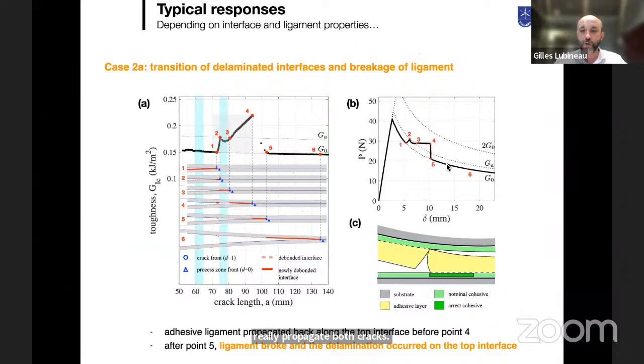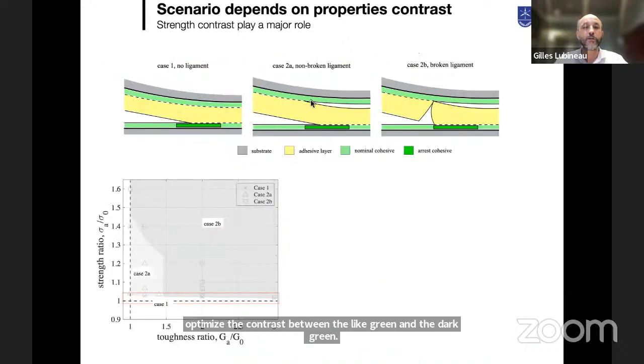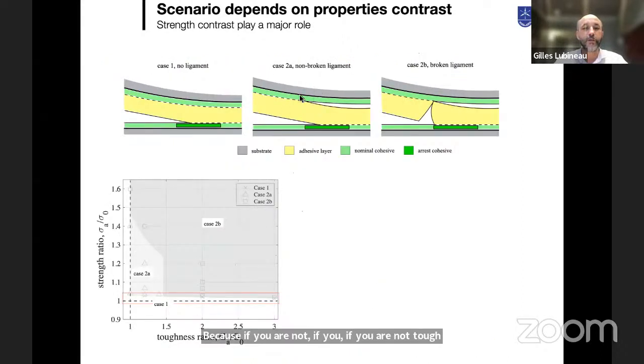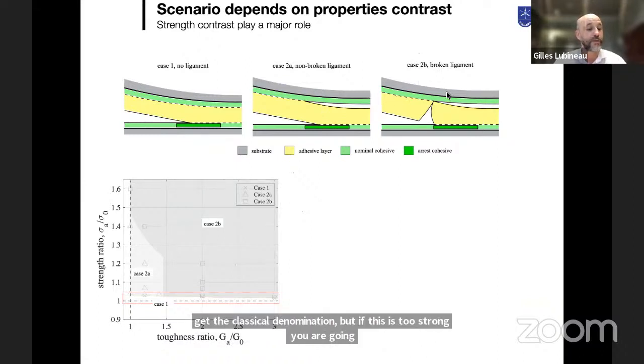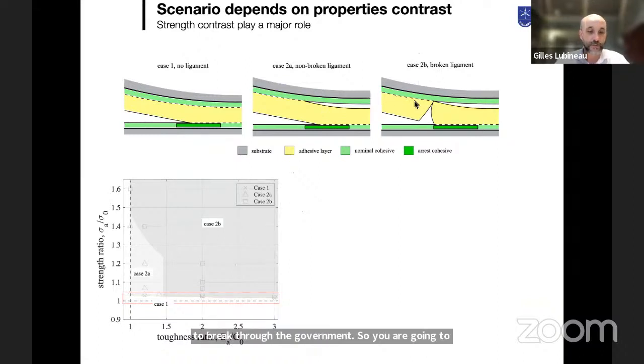You have ligament breakage. So that means that you need to optimize the contrast between the light green and the dark green, because if you are not tough enough, you are not going to get this bridging. So if this is not strong enough, you are going to get the classical delamination. But if this is too strong, you are going to break the ligament. So you are going to limit the performance of your reinforcement.